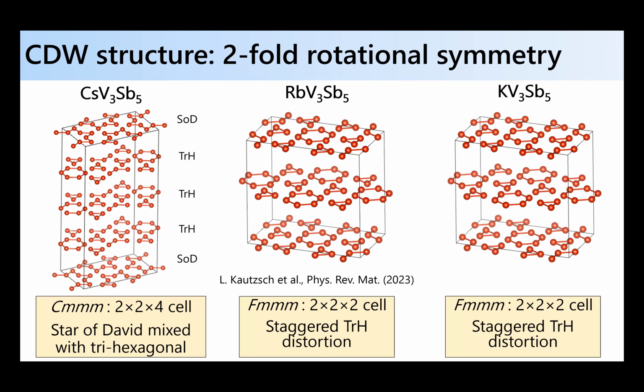Okay, and so the charge density wave states that result in all three compounds are shown here. So the potassium and the rubidium 135 systems, they both form a 2x2x2 supercell, okay? And they form the so-called staggered trihexagonal distortion. So in an individual layer, more or less C6 rotational symmetry is preserved, but one layer is shifted relative to the other by half a unit cell, so you end up with an orthorhombic unit cell, okay?